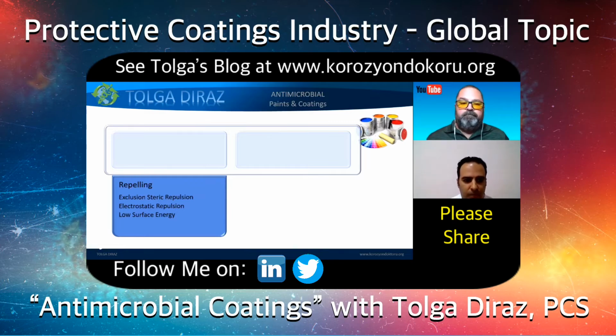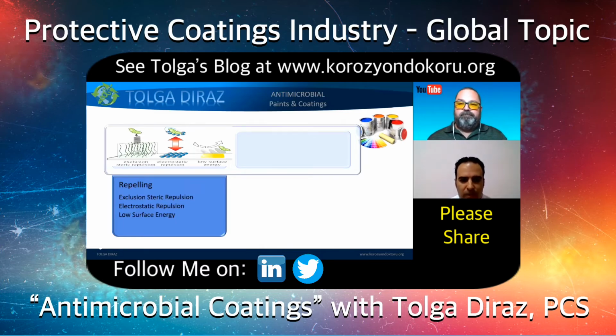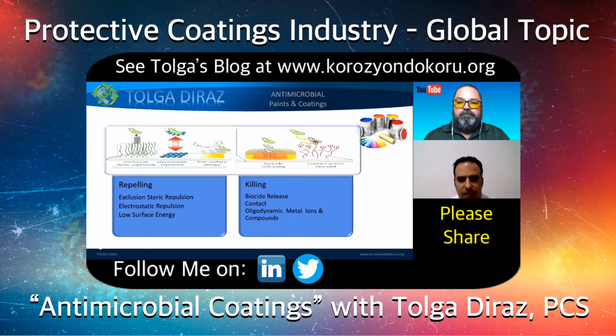For example, by steric exclusion repulsion, by electrostatic repulsion, or low surface energy, you don't necessarily kill microorganisms, but just repel them, anti-adhesive. So it is a special kind of antimicrobial paint. But you can have biocide-releasing or contact-active biocide. That's killing. It's less well known in today's world, but there is also the repelling one.